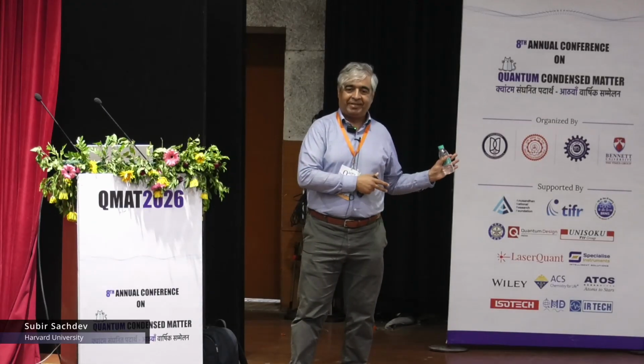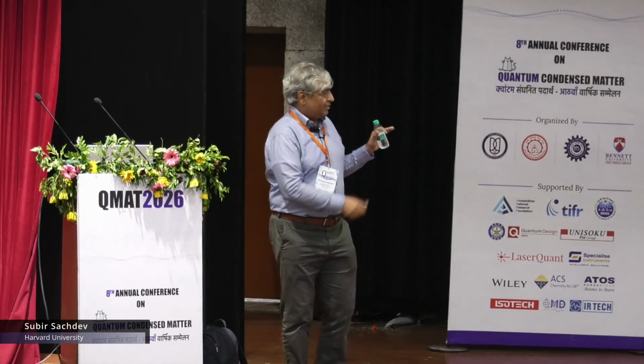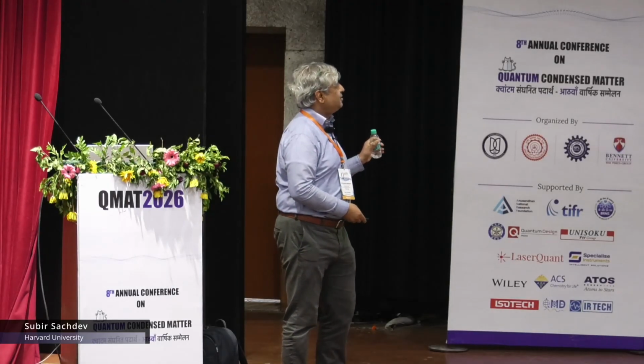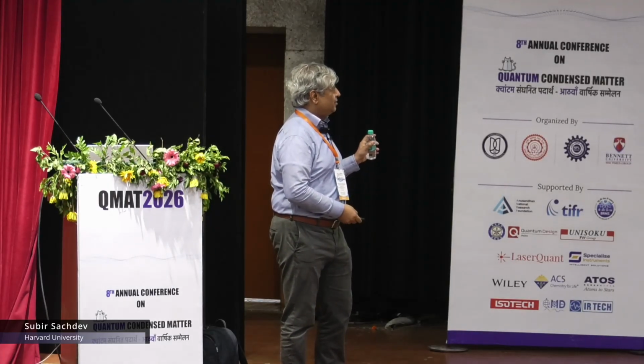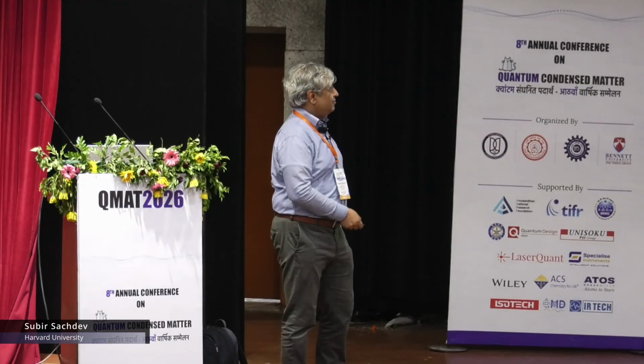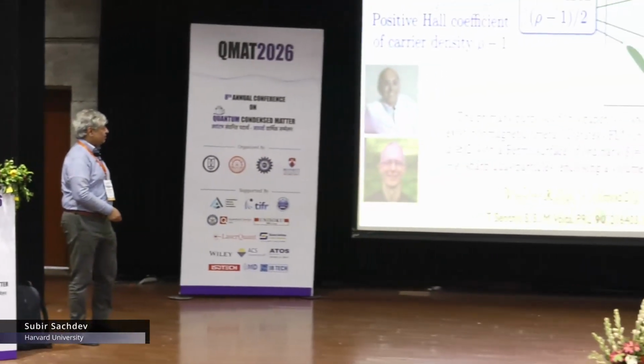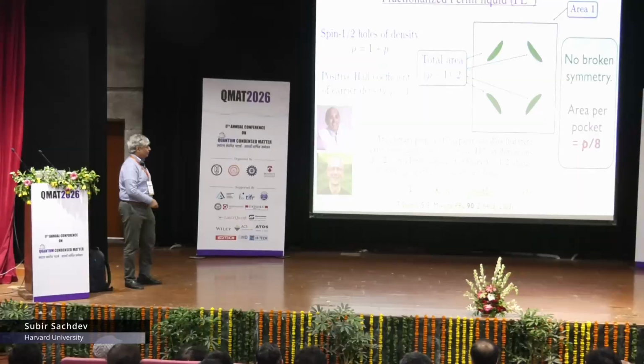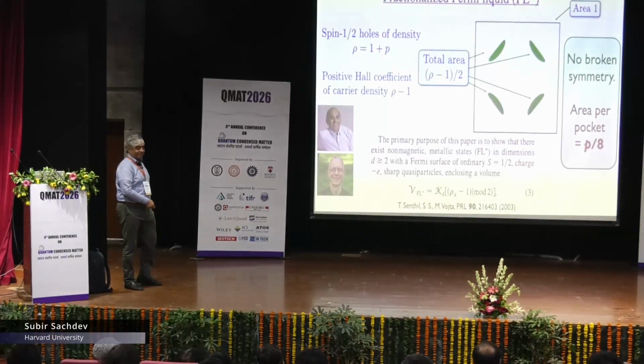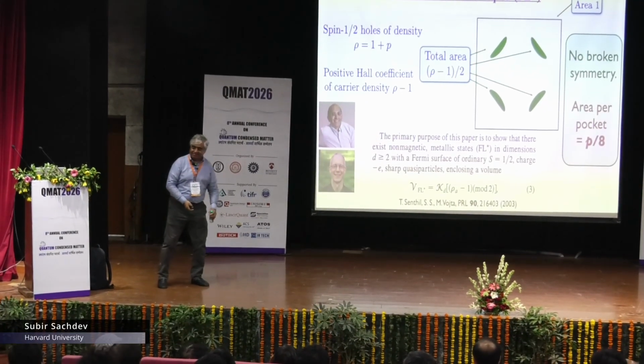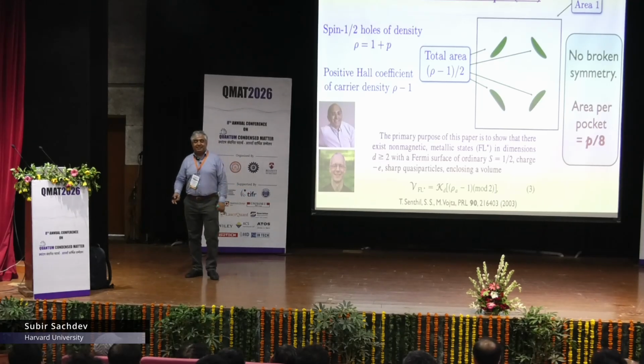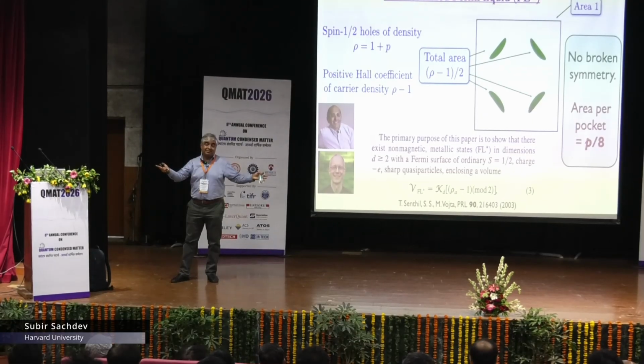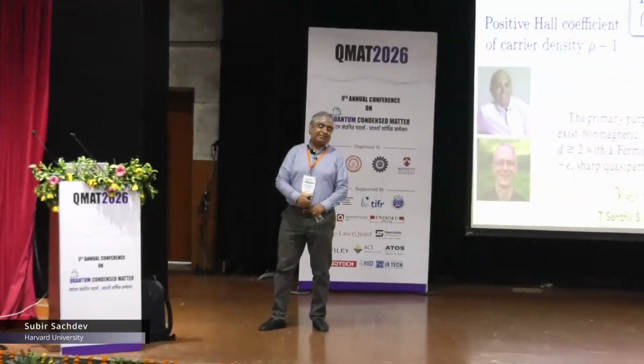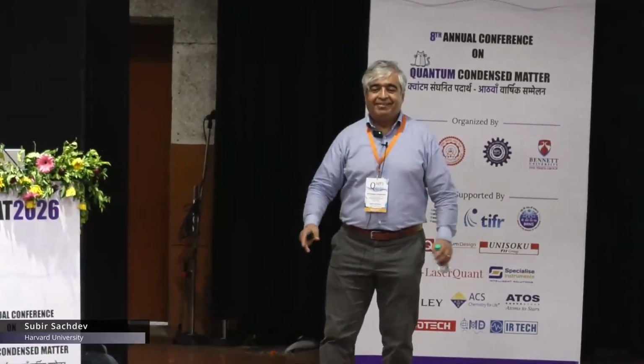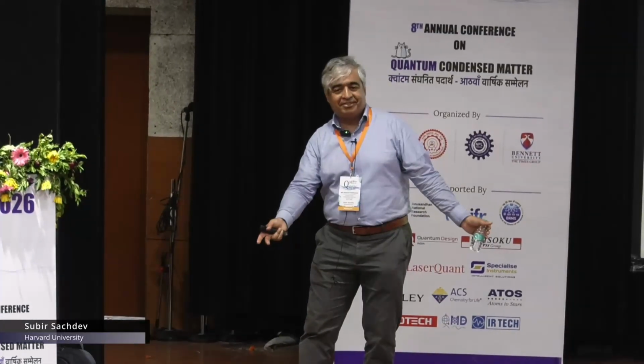So there's a much more complicated theory. But this gives you the thing about this result here. As we said, there are these Fermi surfaces which must satisfy this quantized relation, that you remove exactly one from the density. When you have something that's quantized, as is very familiar in topological physics, if somebody gives you a particular band structure that must have some topological quantization, you say, well, let me just take the simplest possible band structure which has exactly flat bands and which has the same feature.